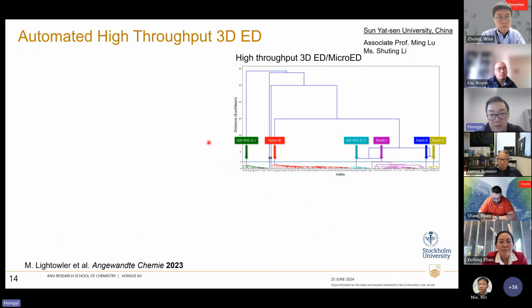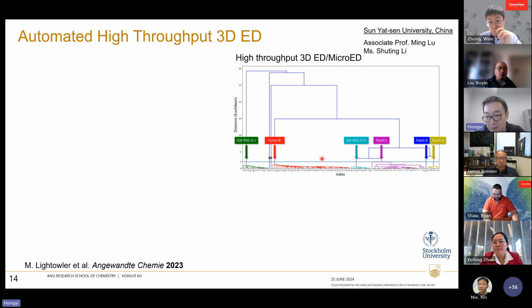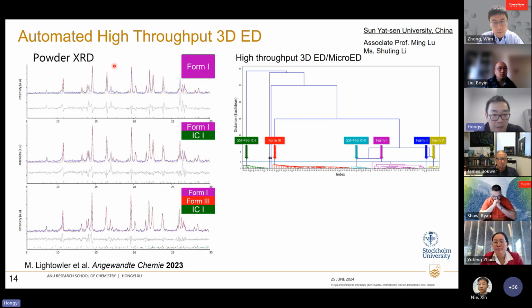Right, so if we look at the data processing, it's automated through a script-based software that was developed by Steph Schmitz, one of the postdocs previously in the group. And then all the data were processed automatically and clustered automatically. So from this cluster analysis, because the unit cells were quite accurate, it was very easy to cluster out these 6 different forms just by looking at the unit cell parameters. And then if we look at the powder XRD comparison, if we just put in form 1, which is the dominant phase, we see that there are several peaks that were not indexed. So this is an indication of additional phases. Then we put the inclusion complex 1 phase in, and there's still a few peaks not identified.